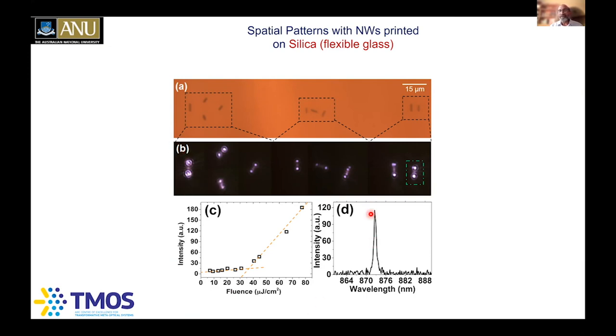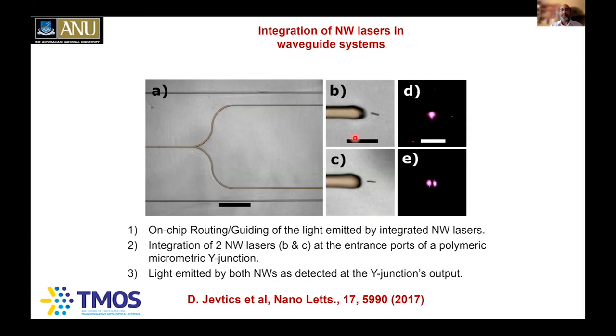And then you can also see very sharp light emission, a narrow line width, which is indicating it's a laser. Again, threshold-like behavior indicating that all these nanowires are lasing, indicating that this transfer process is a gentle process. You're not creating any damage during this transfer process, for example. So they've transferred these nanowire lasers in front of this Y junction polymer waveguide, SU-8 waveguide, for polymer optoelectronics